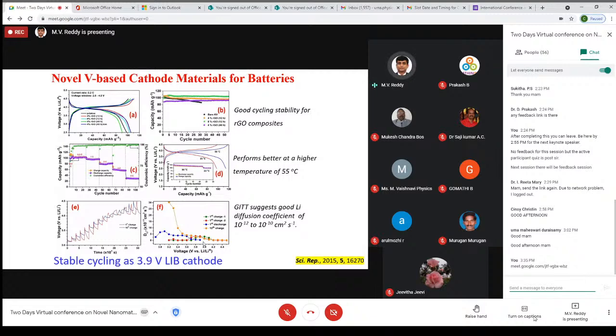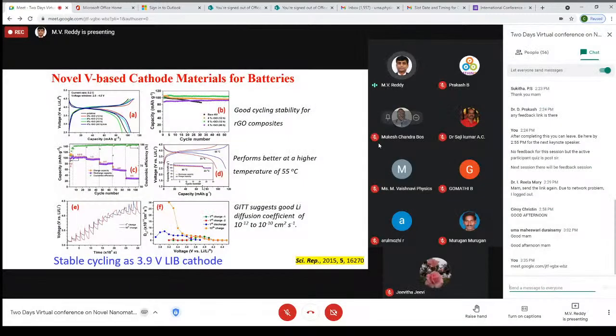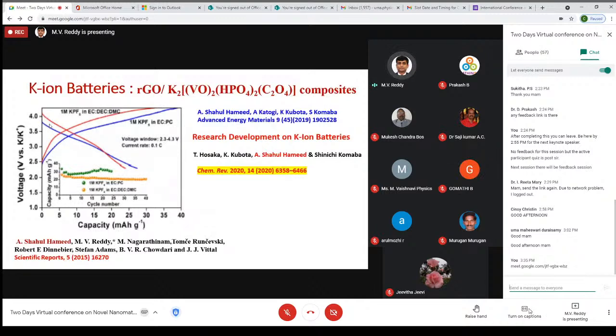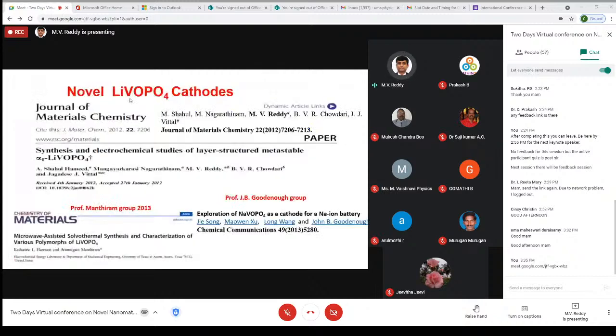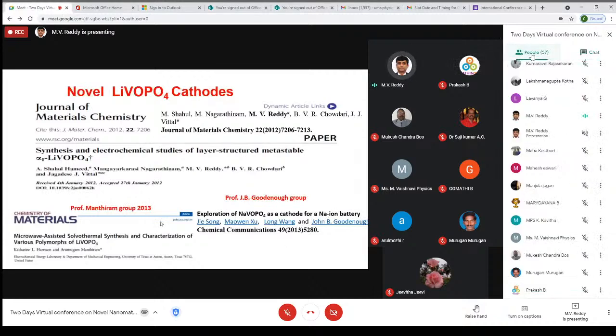Again, we checked a lot of charge-discharge studies, and we checked with impedance. Suppose you work with, for example, sodium and potassium batteries, we also look at them, again due to mobility. I told you that if you go for larger ions, there are mobility and electrolyte issues, so capacity is low. Still, recently some of these materials have been relooked at by other researchers, and they are able to get improved performance. So some new materials we have been working with are phosphate cathodes. In fact, after our publications, some well-known groups have looked into them in a different way, with improved synthesis, etc.